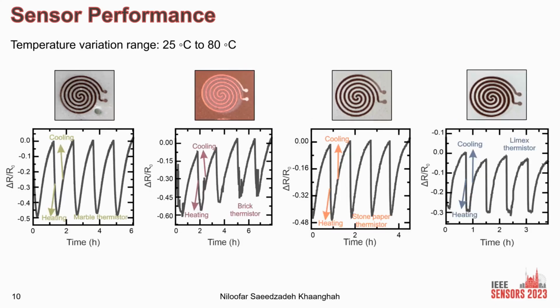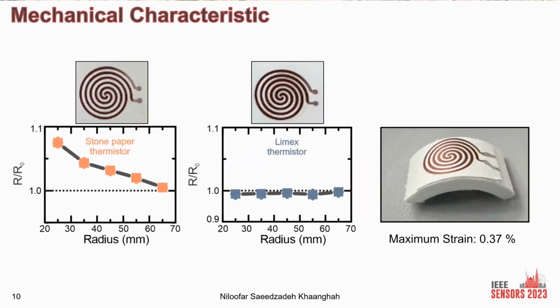Here you see the cycling plots just to check the stability of the signals. As you see, the marble is the most stable thermistor. The brick has some drift, but is still okay, and the other 2 are also somehow okay. And for these 2 flexible thermistors, I also did the bending measurements. As you see, the normalized resistance value for the Limex stays more or less the same. But for the stone paper, we have a slight increase going to the smaller bending radius. The maximum strain at the 25 millimeter bending radius is 0.37%. And also the stone paper stopped working after this maximum strain.